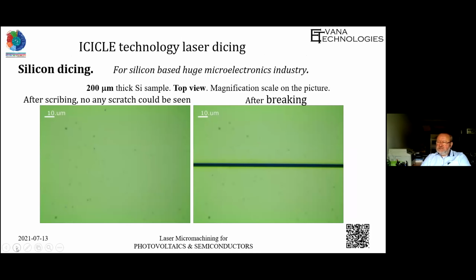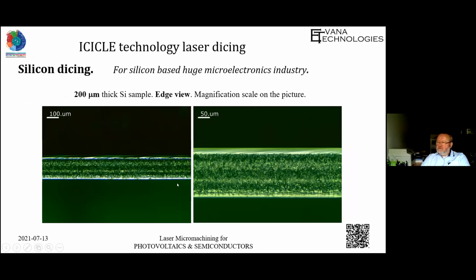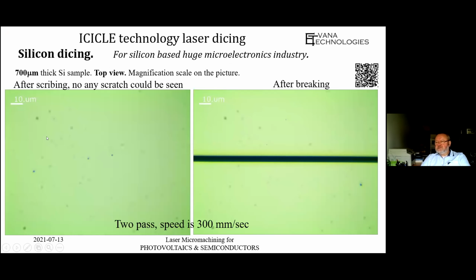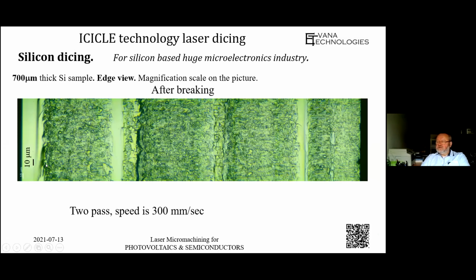Next are a few examples for thicker silicon. After dicing, you have no sign of the dicing line. After breaking, you can see the line. Here is a cross section of 200 micrometers thickness of the material. Here, on the other side, is 700 micrometers thickness of the material, and you can see after scribing and after breaking a straight line. Here you can see the cross section of the 700 micrometers material, with two passes at 300 millimeters per second.